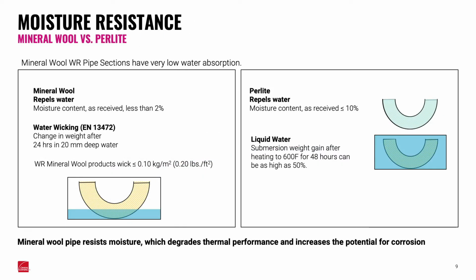We talked a little bit about moisture resistance earlier, and to go into a little more detail, one of the ways that mineral wool and perlite are alike is that they both repel water. Moisture content for mineral wool is usually less than 2%, although it's allowed up to 5% according to ASTM. Our pipe sections are tested in the EN 13472 test, which basically means we're putting this insulation in a water bath, and over 24 hours we're measuring how much water that pipe section will pick up. Mineral wool products in general will be less than 1 kilogram per square meter. Owens Corning's WR pipe sections are going to be less than or equal to 0.1 kilogram per square meter, or 0.2 pounds per square foot, which is really low.